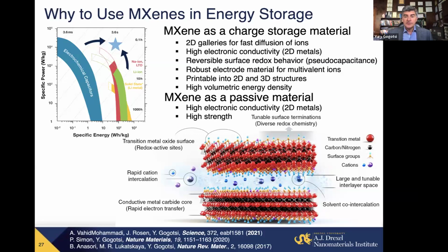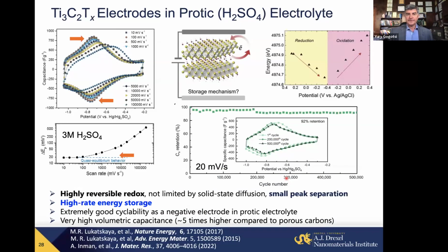But transition metals, niobium, vanadium, titanium can change oxidation states. They're used in batteries to store more energy by redox reaction. So we want to create fast energy storage devices like batteries that can be charged in seconds. Because of much higher electrical conductivity, you can run high current through it and very good ionic conductivity.